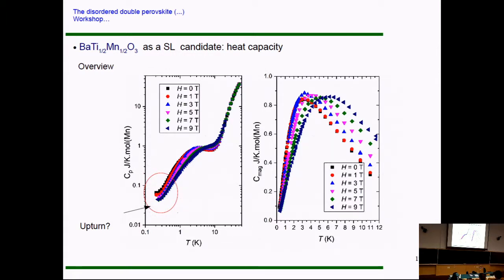We turn now to kind of a new subject. So this is the heat capacity. We can see here it is measured up to 100, and the main features are this bump in the heat capacity taking place around 3 Kelvin, which is really field dependent. And then when you go down, you start to see an upturn here that could be due to a phase transition. I will try to convince you that this is not due to a phase transition, by showing at least 2